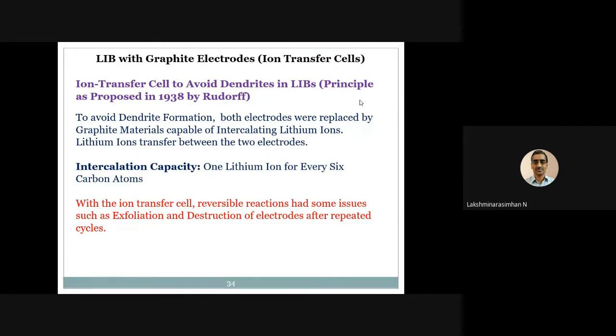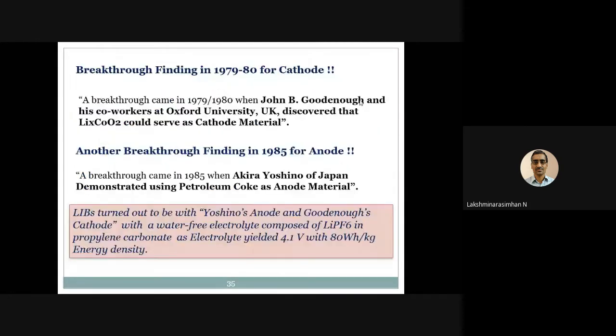But still, there was some other problem, because if you stop one problem, there'll be another problem. The other problem was that the ion transfer cells had some issues of exfoliation and then the destruction of the electrodes after some repeated cycles. So it fell off from the surface where it was coated. All those things happened. So there was again a challenge after challenge.